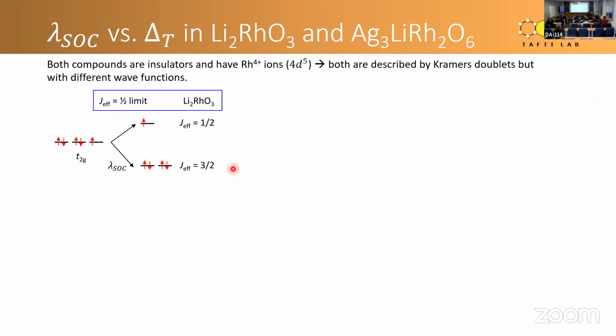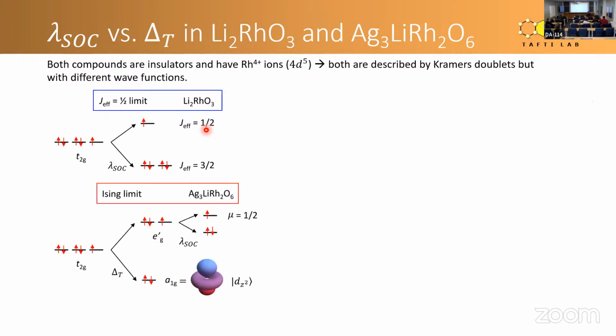So here is how that happens. In lithium rhodate, you have T2G orbitals from rhodium 4D orbitals, and those T2G orbitals split under spin orbit coupling into J effective 3/2 and 1/2. That's the same thing as in the iridates, and you end up with 1 electron in the J effective half. That's the common scheme for iridates and lithium rhodate.